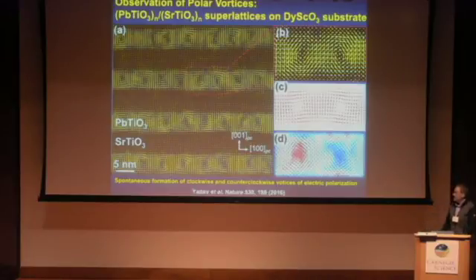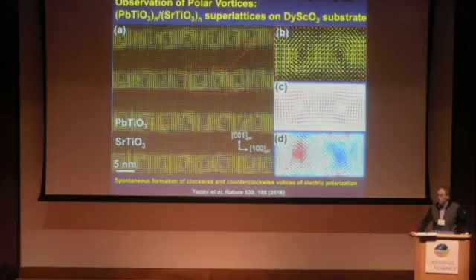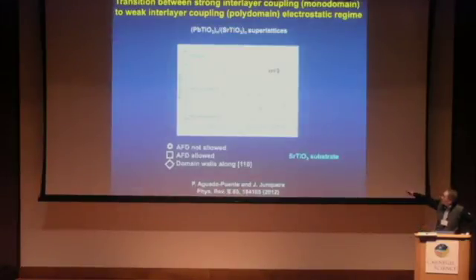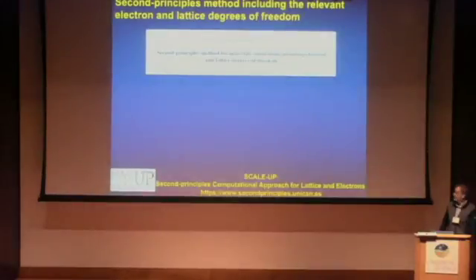The point is that we are at the limit of the things that we can do from first principles. In particular, this calculation here for 3 unit cells of lead titanate, 3 unit cells of strontium titanate, and 16 unit cells of periodicity for the domain includes of the order of 1,000 atoms, and it took more than 6 months to relax. Single shot. So we cannot explore this kind of configurations in an easy way, and somehow we were forced to implement a new simulation method that we call second principles, and is already implemented in a code called Scale-Up.